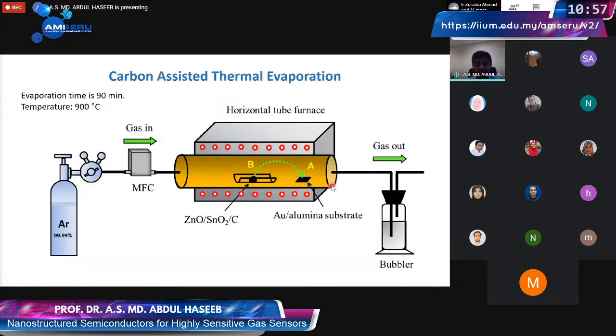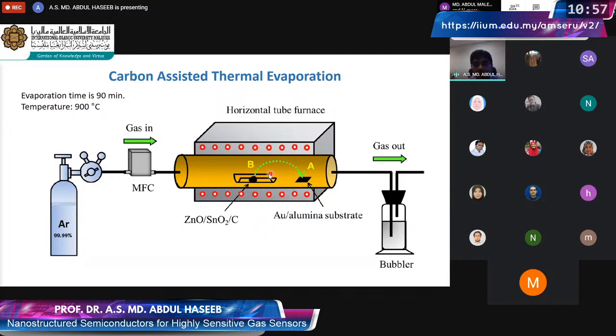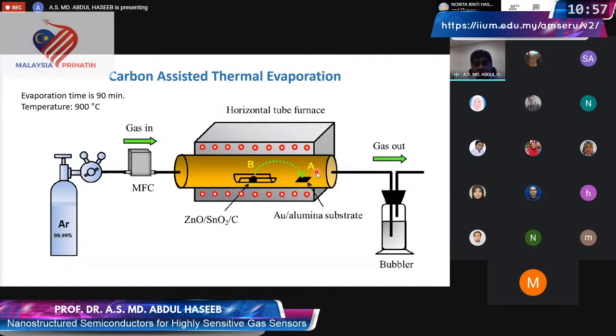Let me show you the setup, which is again very simple. It's a simple tube furnace. Inside the tube furnace, we put a boat, and in the boat, we add our mixture of oxides and carbon. We also put our alumina substrate at a distance from this, about 9 centimeters, and then we flow argon during the whole process.